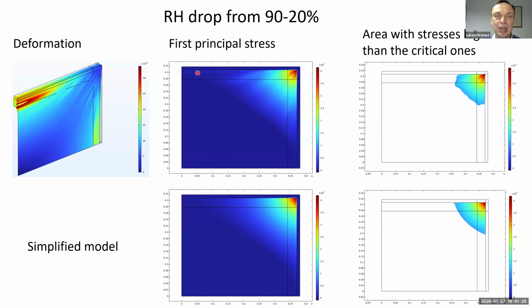Actually, here you have an example where we calculated the deformation stresses in a painting when relative humidity dropped from 90 to 20%, so extremely high relative humidity variation. And you will have the information about the area which is endangered by the cracking.